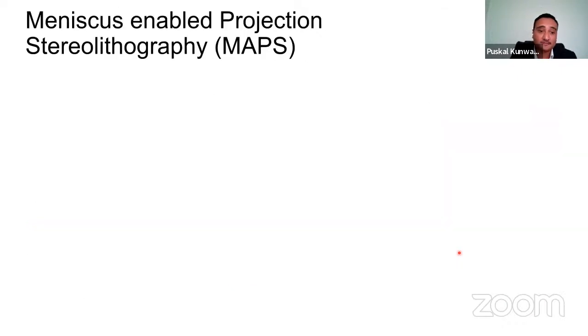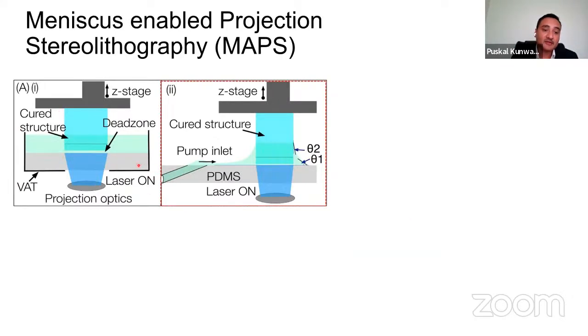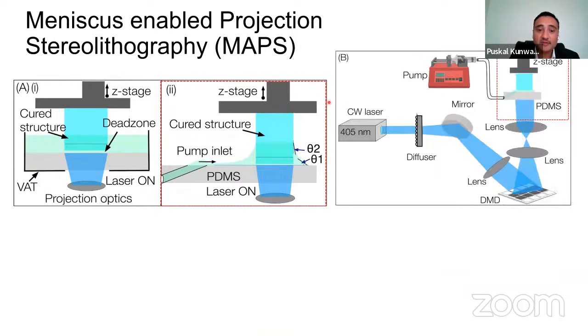Let's see how this works. This is vat-based projection lithography. In place of that, we use our planar PDMS slab, and then we add a pump inlet. Rather than acting as a reservoir, MAPS relies on the generation and continuous maintenance of a resin meniscus formed around an already printed structure. As the print progresses, the material used up is replenished from the inlet pump. This is a simple setup for MAPS.